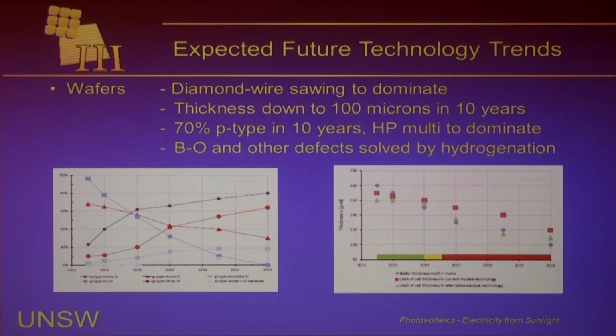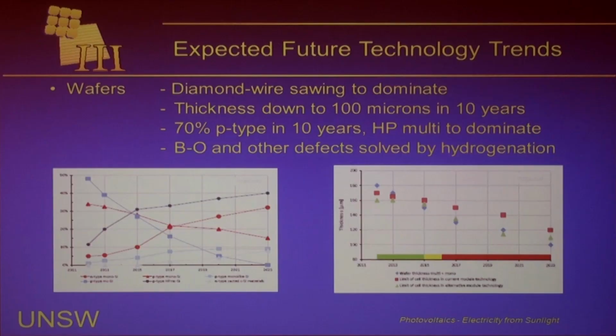A lot of companies are now heading in that direction, and that's why the experts, when they look at it, they're jumping to the conclusion now that the high performance multi here, it's only 10% at the moment, but it's going to be the dominant wafer type by whatever date this goes up to, which is, what, 2023, whatever. Okay, so seeded cast material is no longer the flavour of the month. It's going to be dropping down very substantially, maybe not even used at all. There's still a couple of companies looking at it, but really it looks like this type of wafer may well